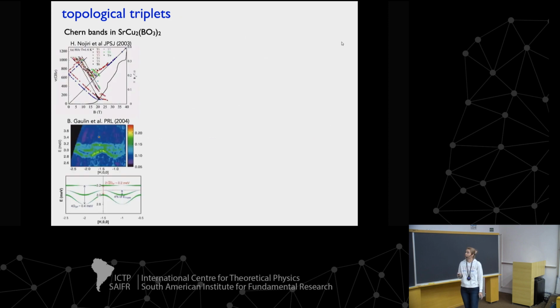In the experiment, what we see is that these bands are split and dispersive, and the same splitting is there in the ESR spectrum at zero magnetic field, and all the way down in the magnetic field as well. So that indicates that anisotropies are important in these materials, and without anisotropies one cannot really describe this system.